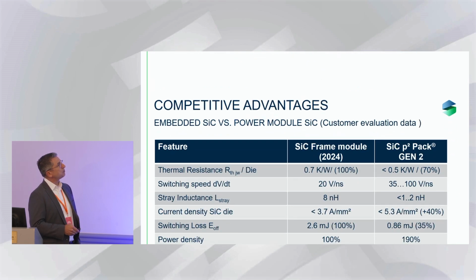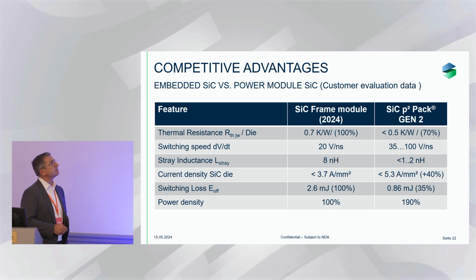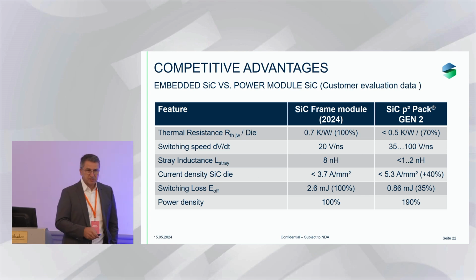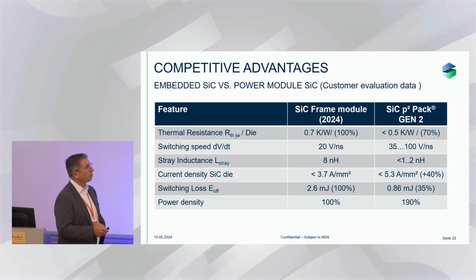And therefore, you now have a summary of the competitive advantages that you find. One of our customers makes his own modules, and it is a comparison with a pretty new module, which is coming this year to the market. They have a thermal resistance of 0.7 kelvins per watt per die. And in our P-square pack generation 2, so organically insulated, it was only less than 0.5. Switching speed was limited to 20 volts per nanosecond with a module. We achieved up to 100 volts per nanosecond with the embedding. And the stray inductance in this module was 8 nanohenry, while we are in the range of below 1, up to maybe 2 nanohenries, if there is not so much design experience.